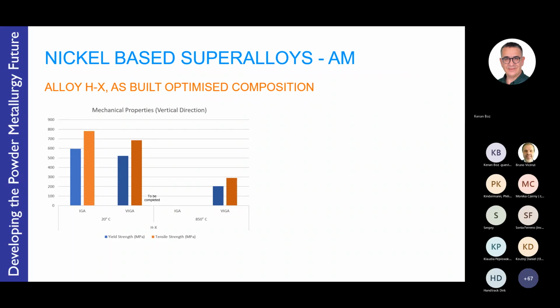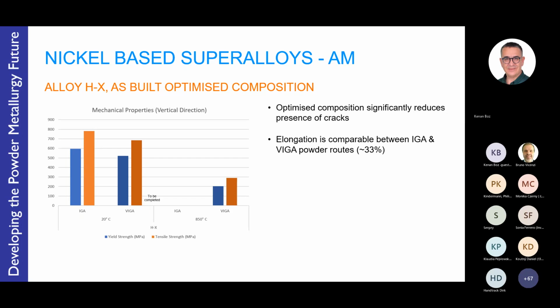Comparing the properties, here we see a comparison of inert gas atomized and vacuum inert gas atomized powders at 20 degrees, as well as operating at high temperature at 850 degrees C. And you can see yield strength and tensile strengths provide very good performance. And yes, there's definitely an advantage when it comes to vacuum inert gas atomizing at high temperatures. However, at ambient temperatures, there's not much difference between them actually. Yes, so the optimized composition reduces the presence of cracks. The elongation is comparable.